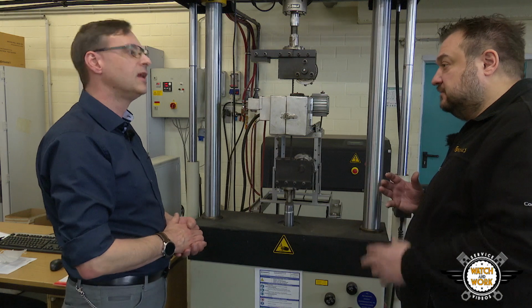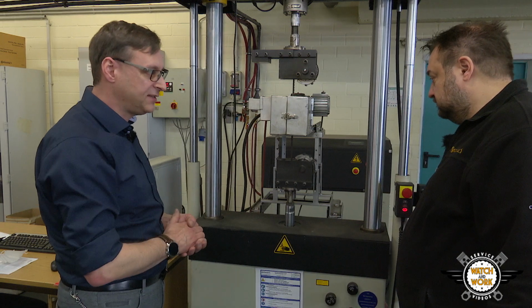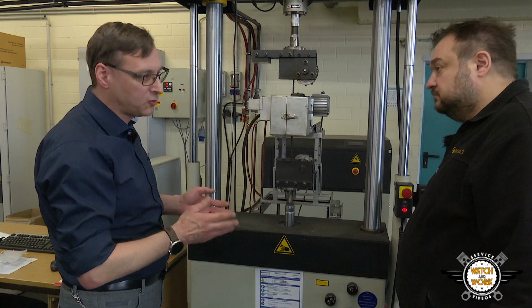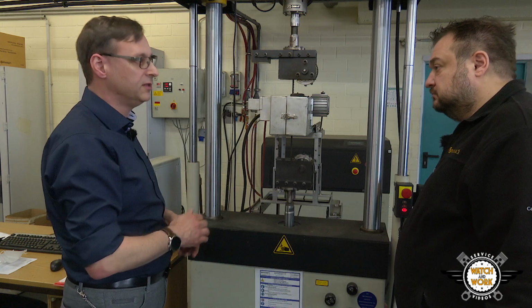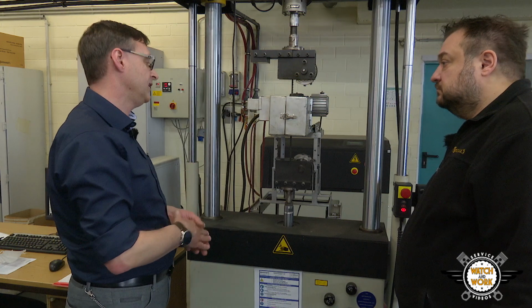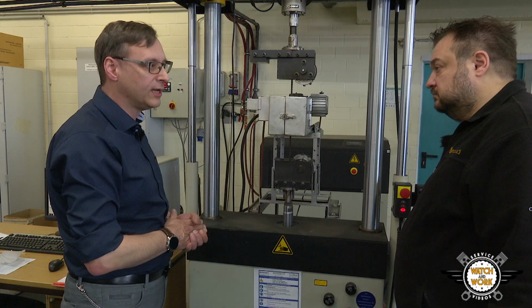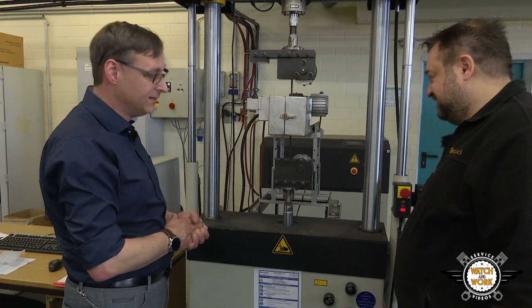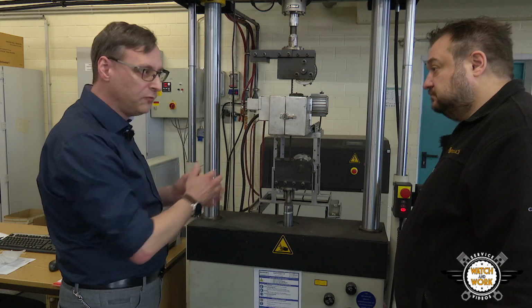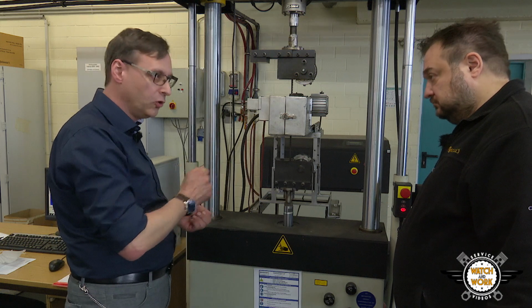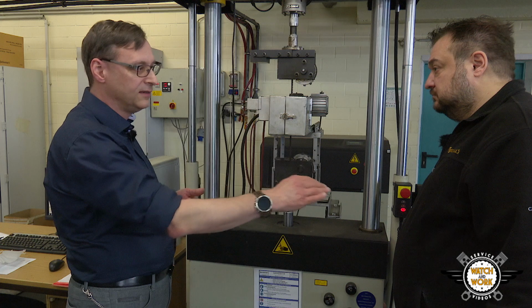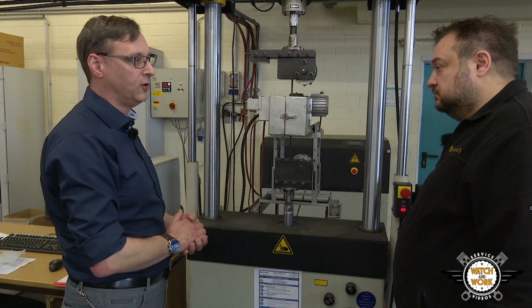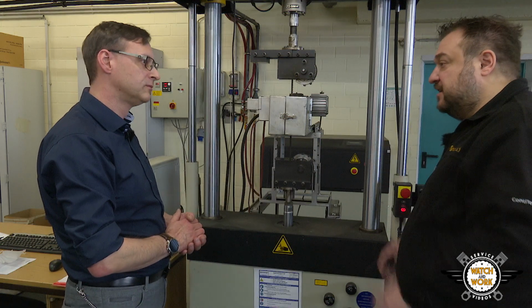So it's a sort of time-lapse test. Exactly, we manage around 1.7 million impulses a day. But the belt will have to endure over 700 million during its lifetime. So we test under overload conditions with increased forces and then work out the belt lifetime at lower forces. Meaning the belts have a built-in safety margin again. Exactly.